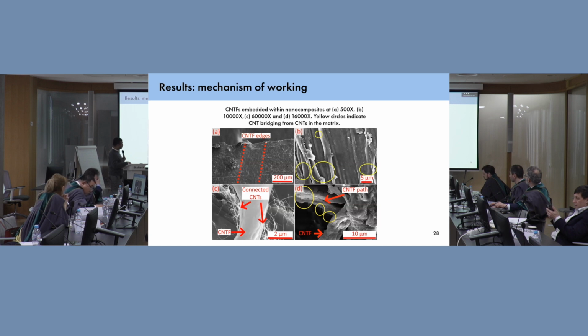So we have a good connection, good adhesion, good wetting here, and we were lucky enough in another place to actually find these CNTs from the matrix actually connected to the CNTF. This may be with the epoxy, it may be mechanical interlocking. We're not able to tell in this exact place, but we also tried to remove a CNTF by tearing it slightly just to confirm this.